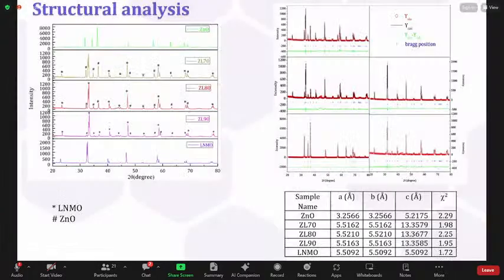So this is the XRD graph, in which the star shows the LNMO part, and the hash shows the ZnO part. It shows no detectable impurity in the XRD patterns, and the XRD patterns were fitted using the Rietveld analysis, which shows the parameters in the table below. So these are very well fitted graphs.